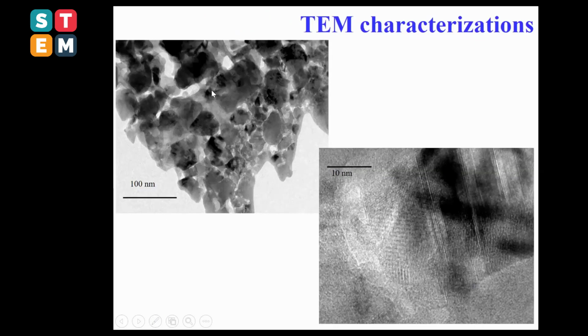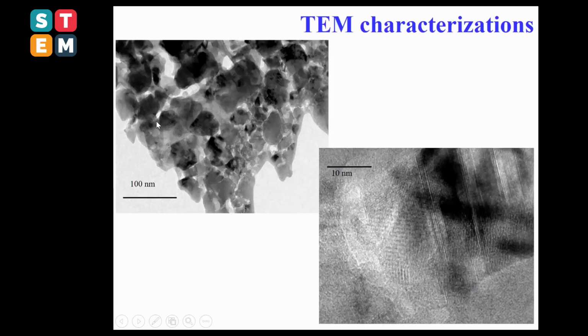Okay, the TEM confirmed this small grain size in these materials, where you can clearly observe here this nano grain size, roughly around 100 nanometer grain size.